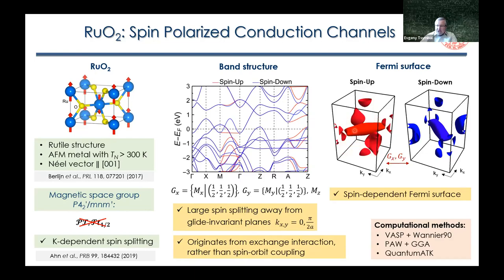As you can see, the shapes of these Fermi surfaces are congruent. So the size of these Fermi surfaces is the same. But they are not the same if you look at specific k points in the Brillouin zone. In fact, they are related by a mirror symmetry transformation. As a result, we should expect that in the conduction, specifically in the process of tunneling, we should have a difference for two spin channels because of different Fermi surfaces.